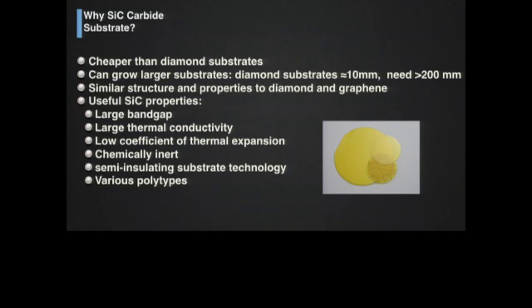And also silicon carbide comes in lots of different polytypes. There are over 150 crystalline structures of silicon carbide that we know about, although 3C, 6H, and 4H are the predominant ones, but there are other ones that include 15R and 2H and all kinds of different combinations of crystalline structures that can form on the basis of growth. Some of these may not be thermodynamically stable, but they may offer some possibility for growth on a foreign substrate.